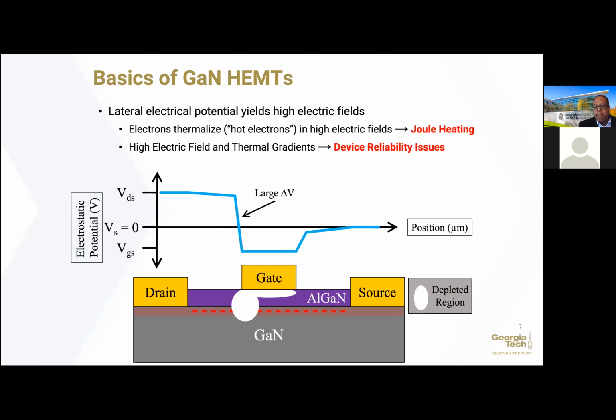And so what happens here is that right here at the drain side edge of the gate, because of this large field right here, I get heating, Joule heating that occurs right here at the drain side edge of the gate. We know this. So this is where the heat generation is all occurring. I can spread this out. So depending on the voltages I'm putting on this device, I can manipulate the shape and the size of that heat generation zone. But nonetheless, it's typically most intense right there at that drain side edge of the gate. And that's what we need to dissipate.